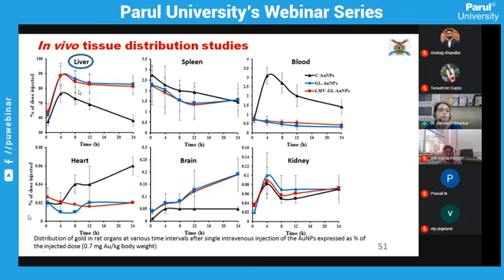And whatever was taken up by the liver, you can see there is a rapid decline in the dose in the case of citrate reduced. But in the case of the glycyrrhizin reduced gold nanoparticles, they were retained for almost 24 hours. Up to 24 hours, we could see the levels in the liver. So this again established that the strategy works, to use glycyrrhizin as a reducing agent, as a stabilizer, and as a targeting ligand.